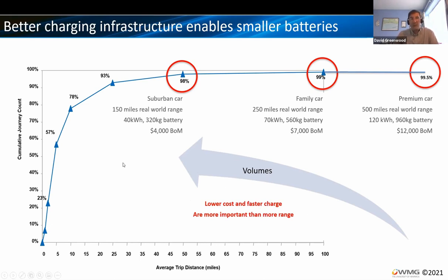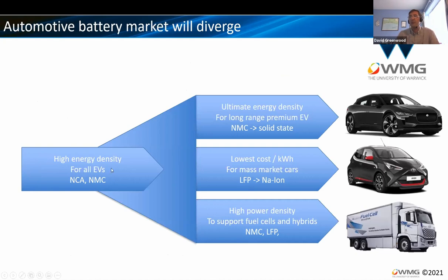And that's quite important when you think about the needs of the chemistry and the needs of the components that we need to go into the vehicle, because it means that where we go is from today, which is where pretty much everything on the road is using an NCA or an NMC type electrochemistry, you're going to see that market splitting into 3 over time. First is that ultimate long range, and you will still see that. You will still have the Jaguars, the Bentleys, the BMWs with a model in the range that's capable of doing 300 to 500 miles range, but there won't be very many of them.